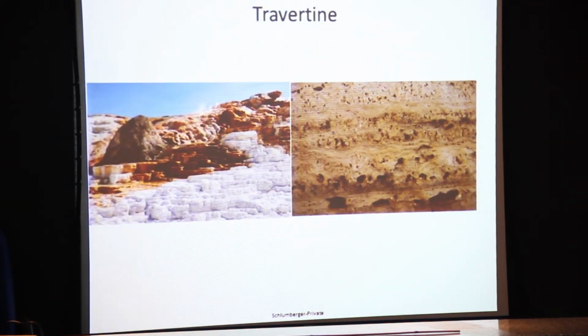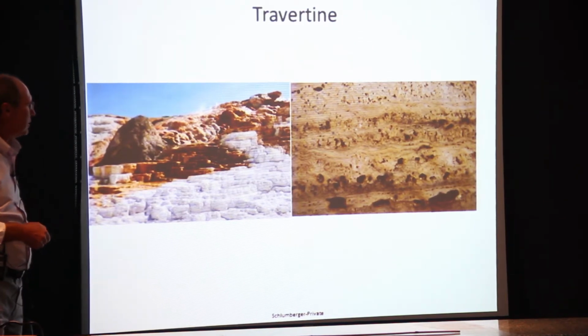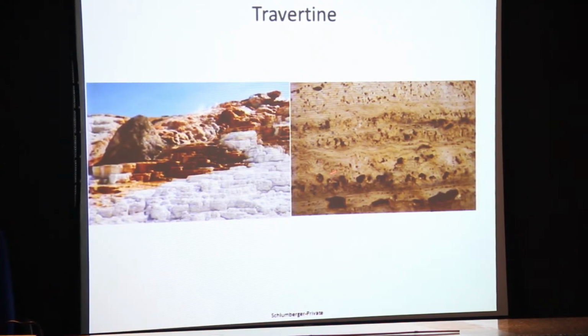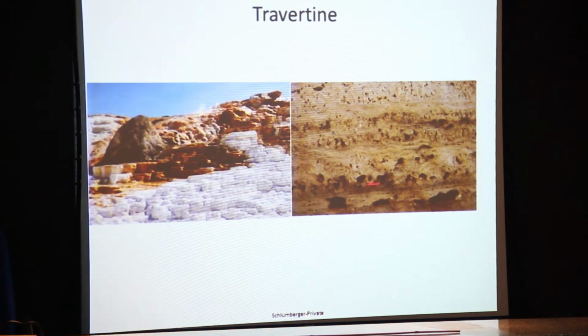Now, in addition to the coquinas and the microbialites, there's pretty strong indications now that there's travertine deposits in the pre-salt. Travertine is normally associated with hot springs where you essentially have calcium precipitated, and you get these vuggy intervals. Very good reservoir. They're not common in terms of oil field reservoirs, but more and more you're seeing indications that travertine buildup can be quite important in some of these pre-salt fields.